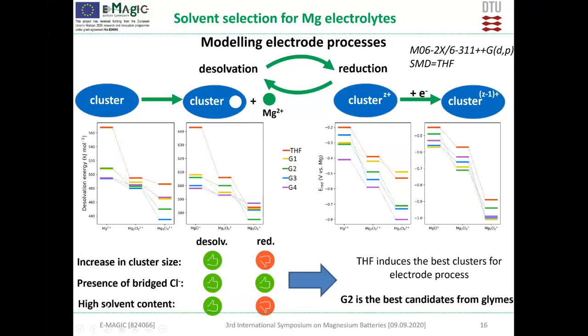A high solvent content also has a positive effect on the desolvation, because if you have more solvent, the interaction between magnesium and chlorine is getting weaker. So because of that, it's much easier to remove it. So based on that, we can see why THF is working so well, because it induces the best clusters that we can see. But if you want to go to some other solvent that is less volatile, G2 is just the best candidate among the glymes.